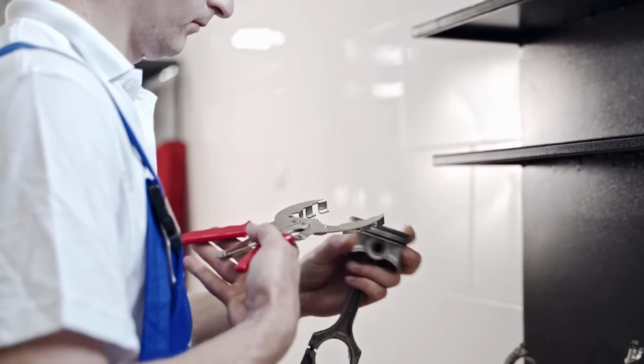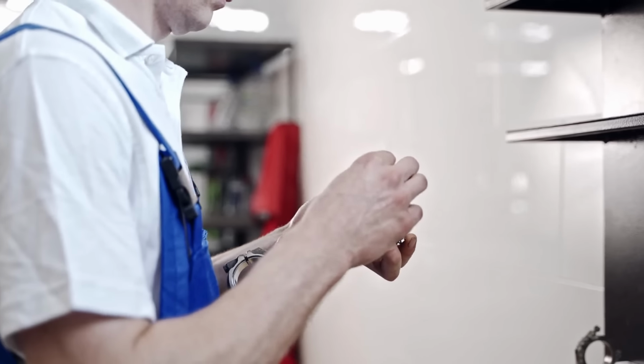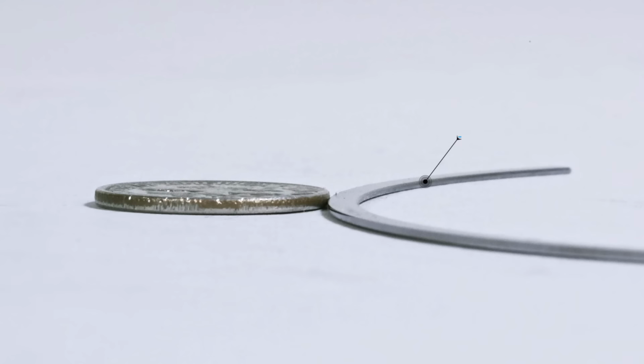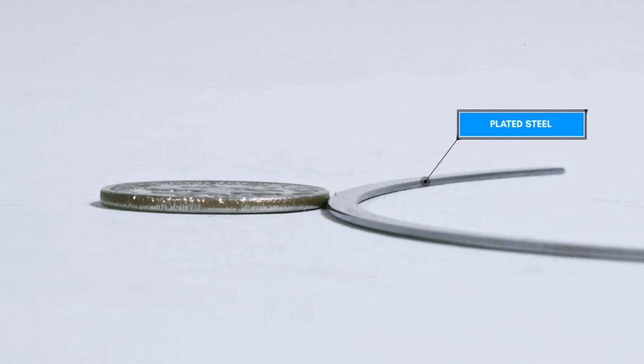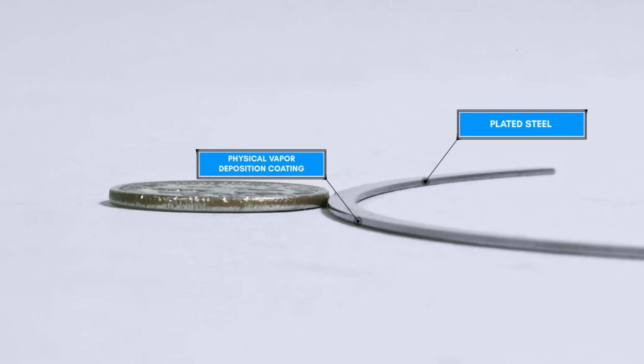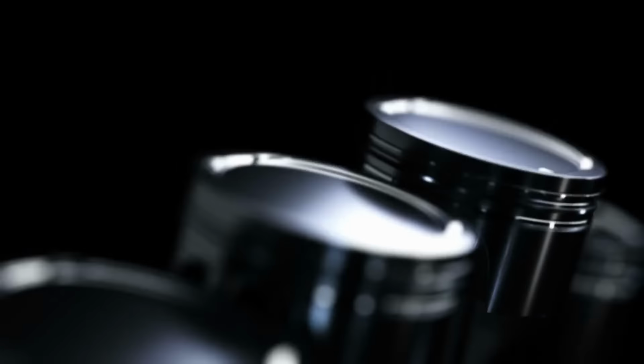The brittleness of iron limited how thin they could be manufactured. This resulted in the development of a thin, phosphated, or copper-plated steel ring that featured physical vapor deposition face coatings that apply hard material layers like chrome nitride directly onto the ring's surface. These coatings minimize friction loss due to their extremely smooth surface and offer high wear resistance. Physical vapor deposition coating rings can maintain their contour longer, allowing for reduced ring tension and improved friction characteristics.